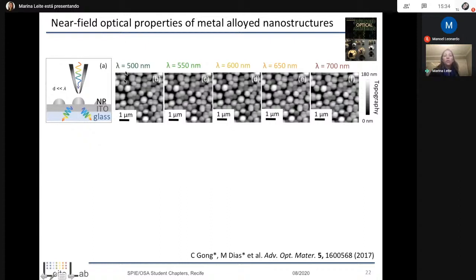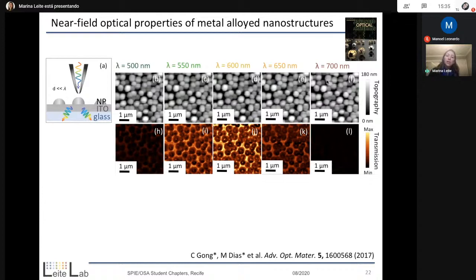So what you're seeing here is a sequence of morphology images, just showing the topography, how there are no changes that happen, so there is no funny interaction between the probe and the sample. Material is intact. And at the same time, we're acquiring information about how much light is being transmitted. So we can see here that at 500 nanometers, it's all very dark. So not a big deal. Quite a bit of light has been absorbed. Eventually, at 600 nanometers, at resonance, now we're talking about that localized surface plasmon resonance of these nanoparticles. You can see that it looks really bright, much brighter than in the other cases. And essentially, we're wondering, okay, we have this little dot, we have all this brightness around the particles. So what's going on here?